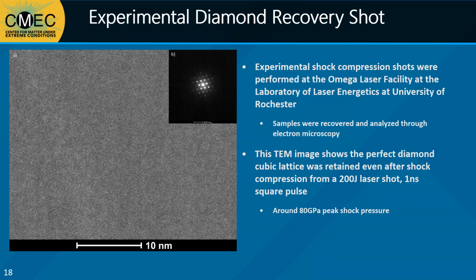Still, we can see here the results of a 200 joule, 1 nanosecond shock reaching a peak shock pressure of around 80 gigapascals. After recovering the sample and analyzing it under TEM, we see that it retains its perfect diamond cubic structure with no dislocations or defects. The diffraction image here corroborates this perfect crystalline order in our diamond sample.